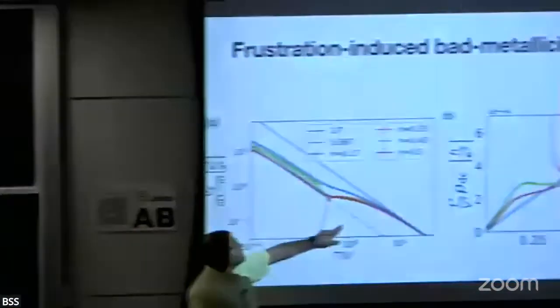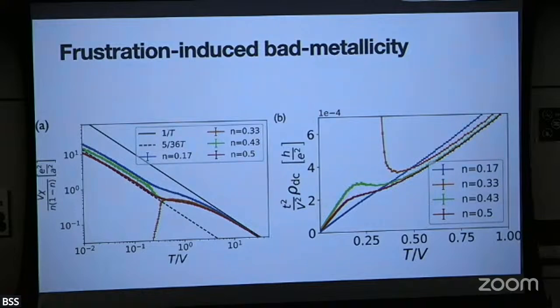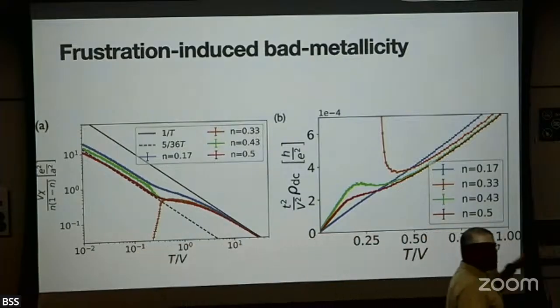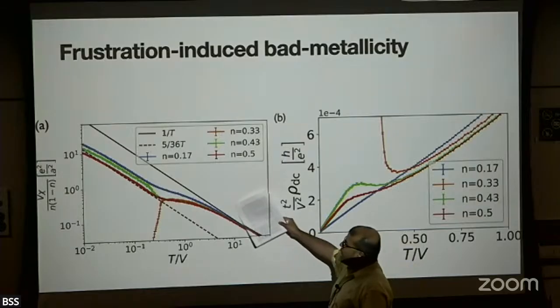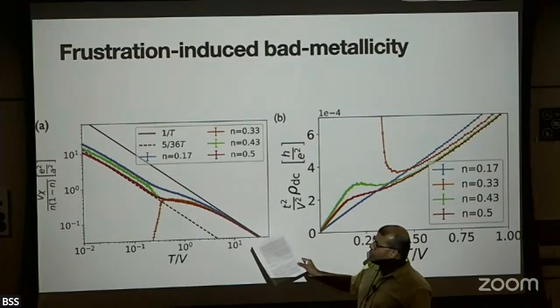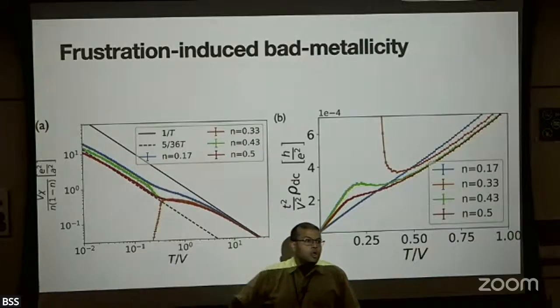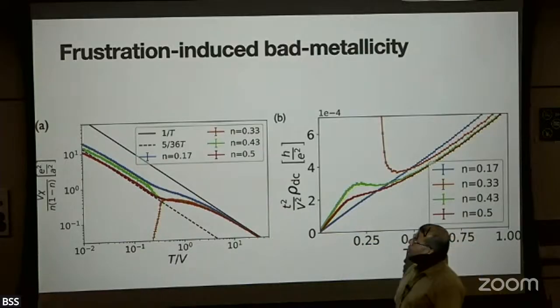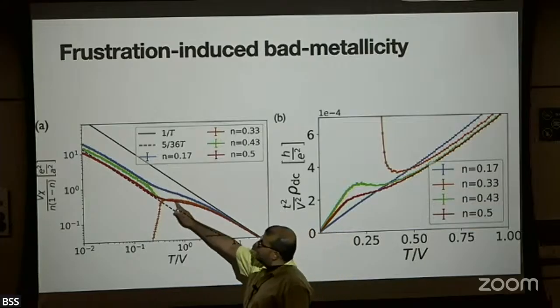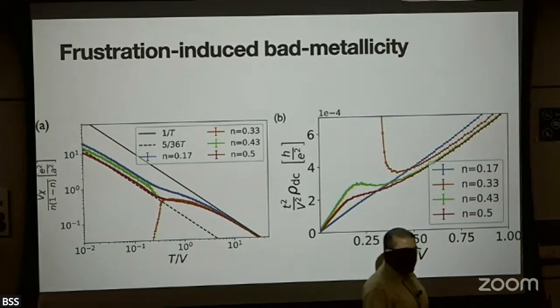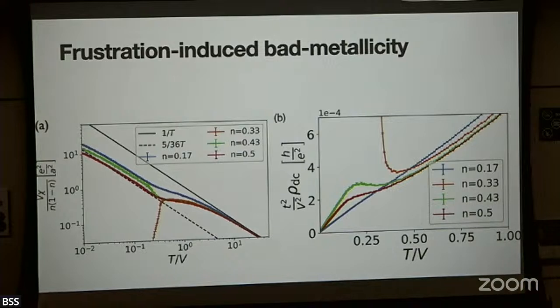This dashed line that you see is precisely that result. It's also 1 over T, and that's because the nearest neighbor antiferromagnetic Ising model doesn't order, okay? The susceptibility is 1 over T all the way down to 0 temperature, okay? And so you see crossovers from a high temperature trivial 1 over T to some correlated low temperature regime, okay? And also if you happen to be exactly at 1/3 filling, the compressibility drops because that's where you're really going into this insulating CDW-like regime, which is dominated by the nearest neighbor repulsion.